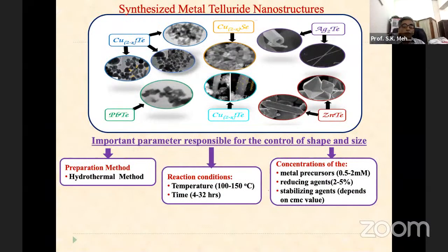So all types of systems were created: copper telluride, copper selenide, silver telluride, zinc telluride, copper telluride again, different types, and you have lead telluride also. So, important parameters which were used: we used the hydrothermal method, with a temperature which varied between 100 to 150, and time was 4 to 32 hours depending on the particles which we are creating.